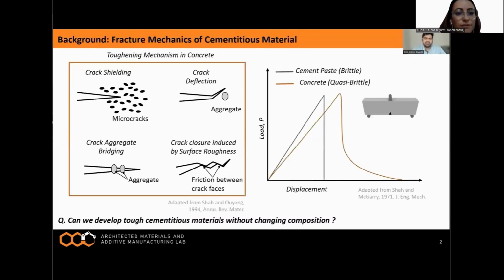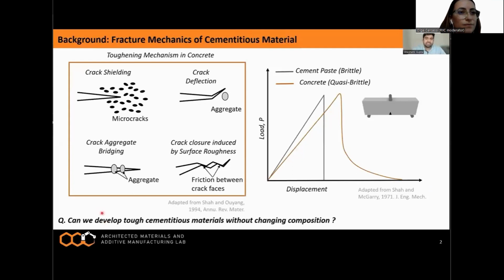Let's start with a bit of background. Ordinary concrete has limited ways to dissipate energy in the process of fracture. This is due to limited toughening mechanisms such as crack shielding due to micro cracks, crack deflection, crack aggregate bridging, and crack closure induced by surface roughness. These limited toughening mechanisms lead to a relatively small length of the fracture process zone. Therefore, not to our surprise, concrete materials are either brittle or quasi-brittle under tension.